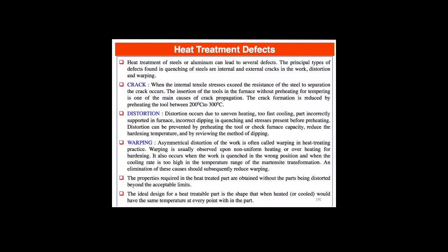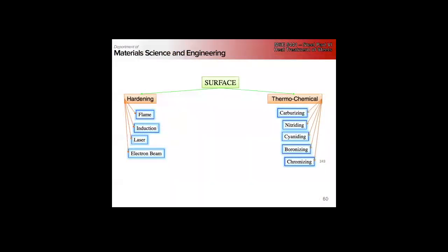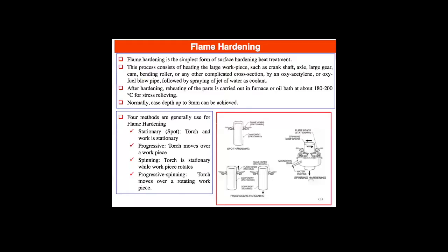Okay, so that's sort of bulk heat treatment processes. In steel, there's also a whole lot of surface modifications that happen, and generally we can think of this as surface hardening, right, by thermal processes, or surface hardening by thermochemical processes. The simplest one is just flame hardening, right? Anyone who's ever done any oxyacetylene welding, right, is very familiar with this, right? Especially if you have an oxyacetylene torch and you make it a slightly rich flame, carburizing flame, right? You can flame harden and carburize simultaneously.